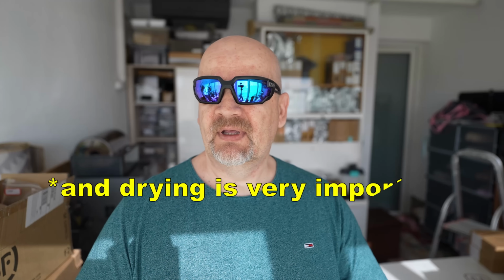Now on the other side it's a little bit harder for printing. I have to use 0.6 mm nozzle, but not 0.3, but smaller layer height, otherwise I have quite big warping. And also I don't like that it's quite brittle material. You saw that on the impact test. Tougher than average PETG, for example, but more brittle compared to the average PA6 CF materials or PA12 CF materials.